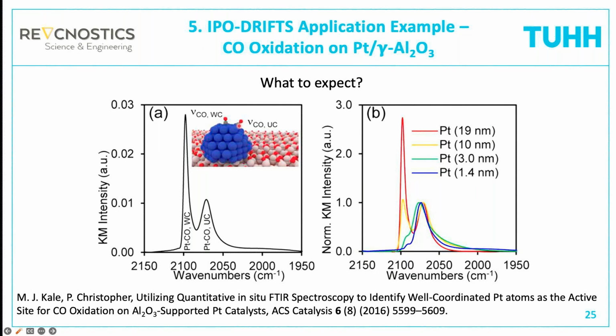under-coordinated platinum atoms that sit at corners or edges, then you get a redshift, and the band moves down to 2070, 2075 wave numbers. Depending on how big your particles are, you get either a pronounced band here at 2100, or if the particles are very small, then there are no terrace sites anymore, and all the CO molecules sit on the highly under-coordinated sites.